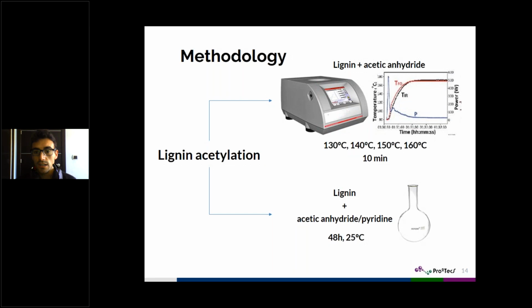Well, for the lignin acetylation, we have chosen two different paths. The first path is the one that you can see at the bottom. We have called it traditional chemical lignin acetylation, and it's just the mix between lignin and acetic anhydride and pyridine in 1:1 volume ratio. This is how lignin acetylation has been commonly done. And in this case, we have selected 48 hours and 25 degrees as the time and temperature of the acetylation.